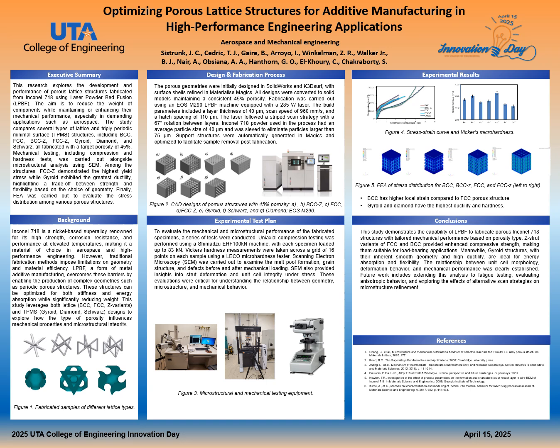This study focused on several types of porous geometries. We included BCC, FCC, which correspond to body center cubic or face center cubic, and their Z strut variants. We call them BCCZ, FCCZ, as well as triply periodic minimal surface structures like gyroid, diamond, and Schwartz. All samples were designed with a 45% porosity level and fabricated using an EOS M290 LPBF machine under carefully optimized parameters. The laser operated at 285 watts with a layer thickness of 40 microns and a scan speed of 960 millimeters per second.